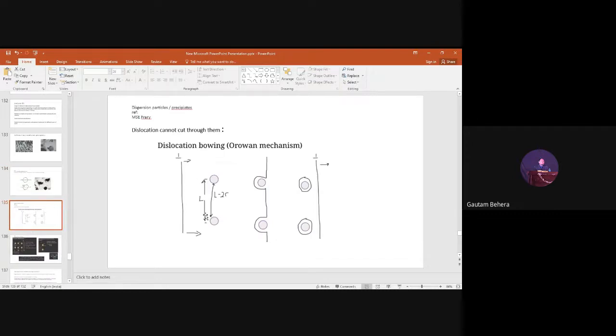And this is a very beautiful image. You can see this is a dislocation line. The dislocation is moving here, and these are the precipitate particles present over here. The distance from the center of one particle to the next is L, and the distance in between the particles is L minus 2r, because the radius is r. The dislocation is moving like this, and it is interacting with the particles. Now what is happening, you can see the dislocation is bowing. This is called bowing of dislocation. The particle size is bigger, so the dislocation is bowing around the particle, and finally it is forming a loop, and the dislocation comes out. And the dislocation will again move or glide easily in the material.